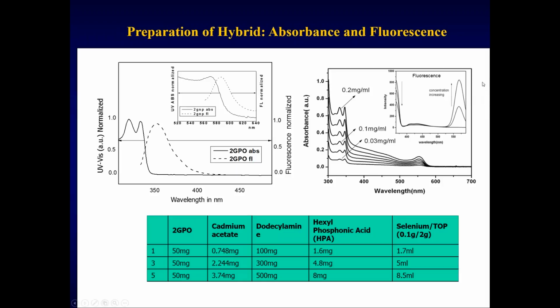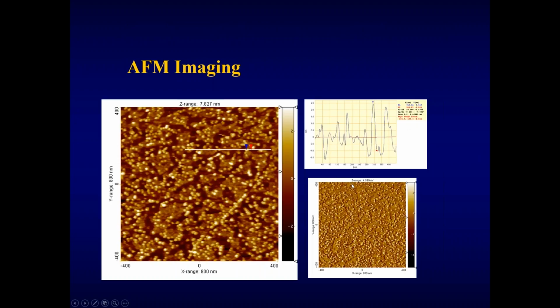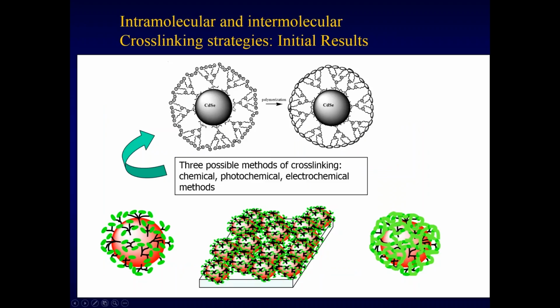And what we did is after electropolymerization, after 50 cycles, we then observed the absorbance and the fluorescence. So what we observed is the shift in the absorbance up to 500 nanometers, indicating the presence of the polycarbazole units. On the other hand, the fluorescence decreased along the polycarbazole unit, but there was retention of the cadmium selenide fluorescence as shown here, which indicates that the cadmium selenide was not changed, but the fluorescence of the carbazole upon conversion to polycarbazole shifted as compared to a drop cast film. So this is the fluorescence actually of a polycarbazole unit.